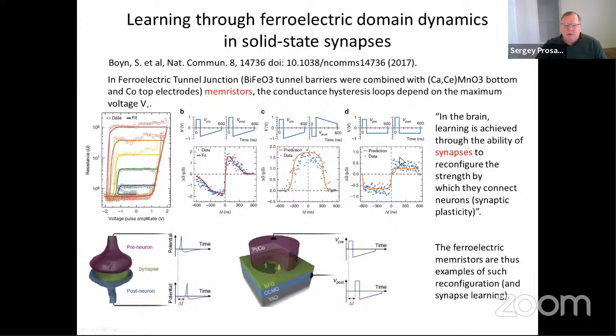One more paper, the first author is Boyn. This is about a tunnel junction made from BFO sandwiched between metals, and you see that in the first slide at the left, they observed a memristive effect, which means that resistivity has a different hysteresis loop depending on the maximum voltage applied to this sandwich. The lower the maximum voltage, the smaller the loop.